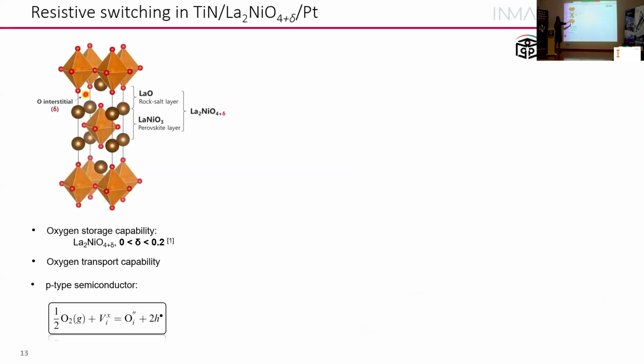So why did we choose lanthanum nickelate? Well, first it was the material of my PhD thesis, so I knew it well. But apart from that, what is good about it? We can adapt to lots of different oxygen stoichiometry. With the same structure, without breaking it, we can have lots of different oxygen contents between 0 and 0.2. So it can transport oxygen because it has a high diffusivity. It's formed by a layer structure with perovskite and rock salt layers. And in this rock salt, we have the interstitials that can move easily within the structure.